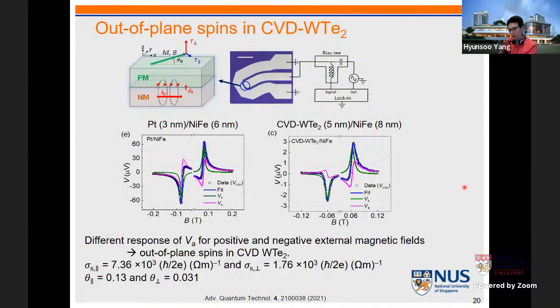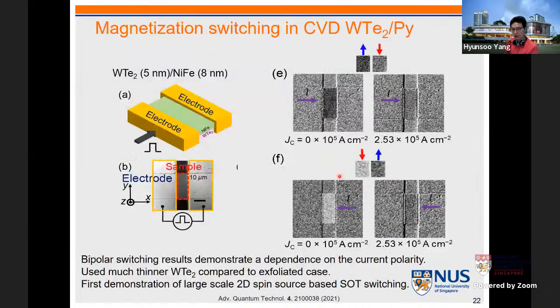Then we can also evaluate the same feature using conventional spin torque ferromagnetic resonance measurement. By looking at the anisotropic asymmetric component of the rectified voltage, you can see our control sample, platinum, has a sort of mirror symmetry if you look at this purple color. But if you look at this CVD tungsten ditelluride sample with nickel iron, this purple color has an asymmetry. So that indicates there is out-of-plane spin texture.